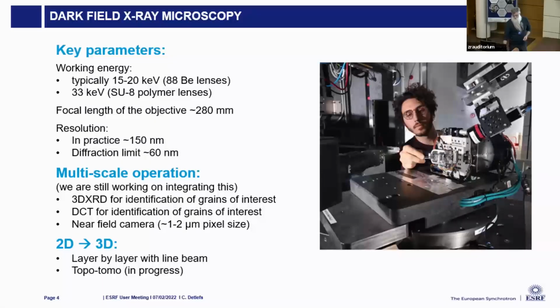And that allows us to do a lot of in situ experiments, which are not possible with electron microscopy. We're working now on multi-scale operation, meaning that we want to combine our very high resolution technique that looks at one Bragg reflection of one crystal grain within the sample, to put that grain into a context, look at the neighboring grains, know what the relation is between the orientations, and potentially in the future also be able to automatically switch from one grain to another and do studies of several adjacent grains or crystalline columns in shells, for example, and things like that.